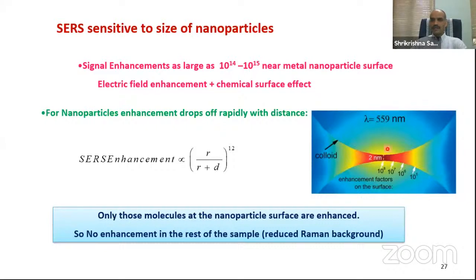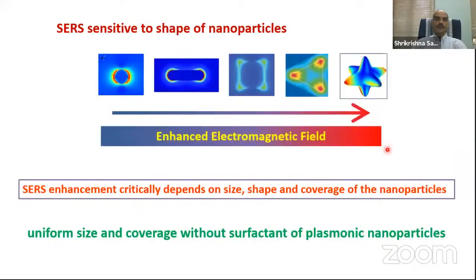Now what does it mean? If these 2 nanoparticles are merged with each other, what will happen? If they merge, then the probe molecule will not be in contact with them, and obviously if the particle is getting bigger, the LSPR, the localized surface plasmon resonance peak, will also occur at a different position, and therefore you will not get that much enhancement. So the first thing we have to see is that only the probe molecules which are in contact with the metal nanoparticle surface get enhanced. And therefore there's a very nice term we call the hot spot. Hot spot means the spot where the probe molecule is in contact with the metal nanoparticle.